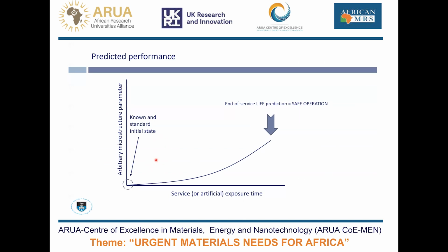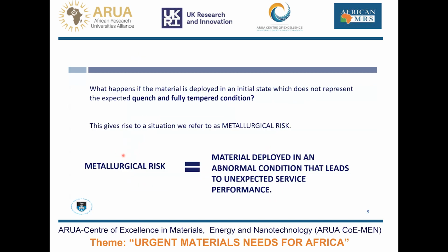Now, that all works very well if we have a situation where we can clearly predict performance. So this is a very simple graph, once again indicating an arbitrary microstructure parameter on the y-axis versus service or exposure time on the x-axis. And if we take a material in a known and standard initial state, as we would expect if we deploy a quench and tempered material in a known condition, then that material's microstructure will change over time, and eventually, of course, it will reach an end of life. But because we measured that, we of course get an end-of-life prediction, and we can then work out safe operation. And all is fine and great, and perhaps there's no need for further analysis because we know everything, and everything is going to work according to plan. But of course, that's not the case.